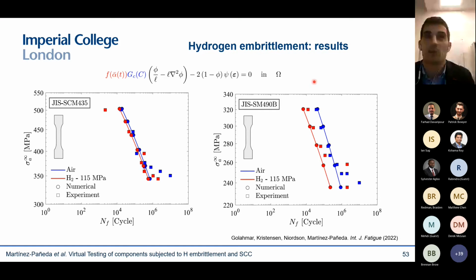One of these is we can compute virtual SN curves. This is what you see here. So these are two different materials. And of course, as you know, SN curves have a lot of experimental scatter. But you can see that we get a very good agreement with experiments, with no fitting whatsoever, just by adding the hydrogen into the picture.